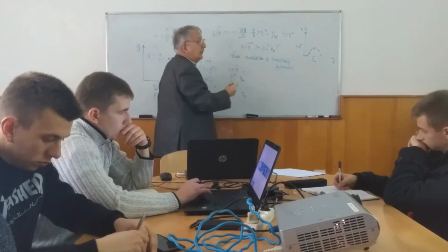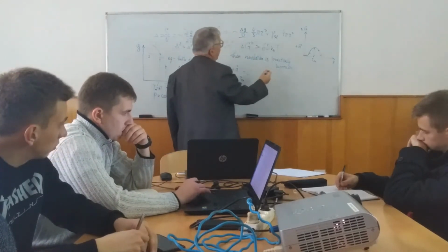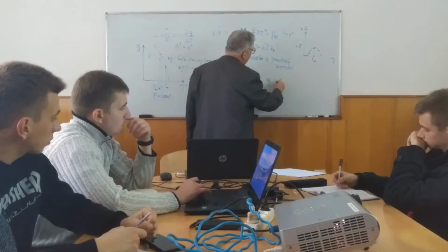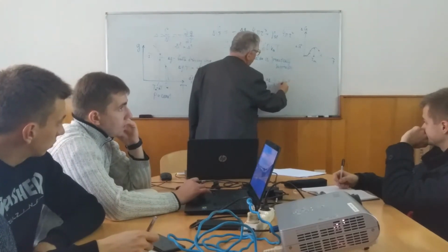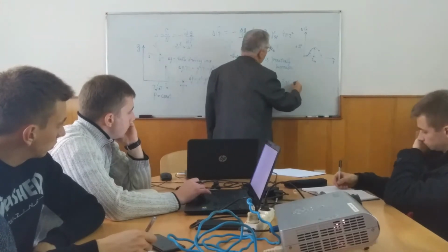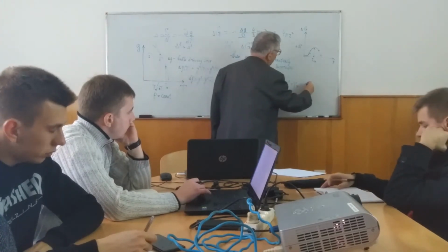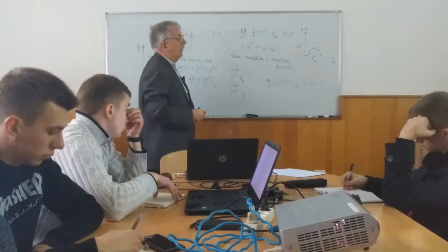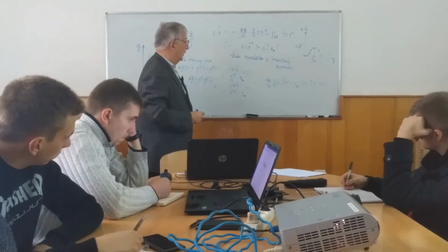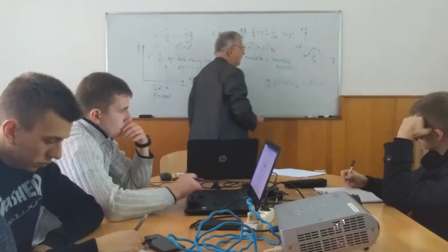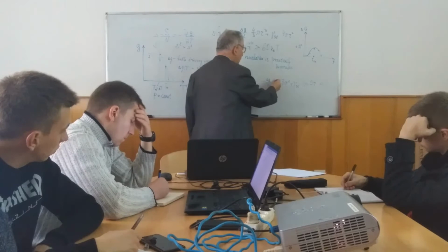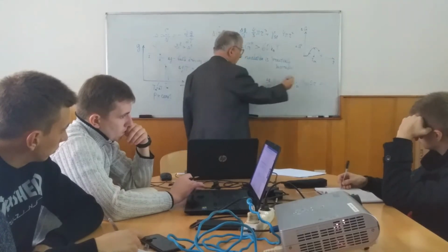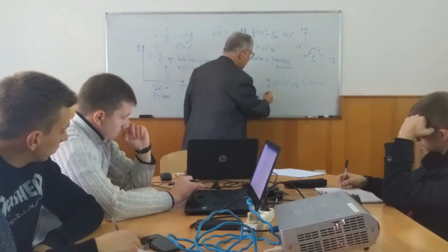So if you take the first derivative of this function over r, of course we obtain minus delta G divided by omega, 4 pi over 3, multiplied by 3r squared. Of course 3 and 3 are constant. Plus gamma SL multiplied by 4 pi multiplied by 2r, and this is equal to 0 if we look for zero first derivative. Since on the right hand side we have 0, we can cancel 4 pi. We'll not cancel so far. We'll write it in the following way.